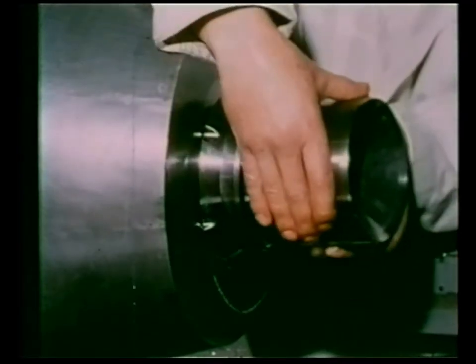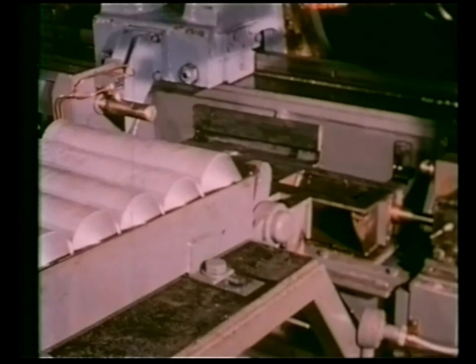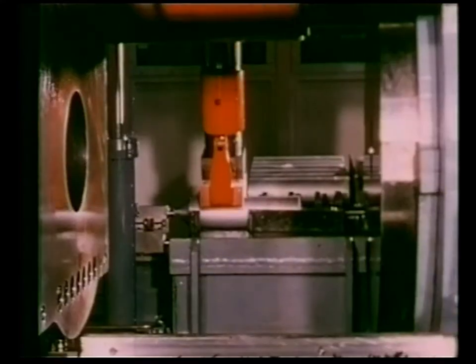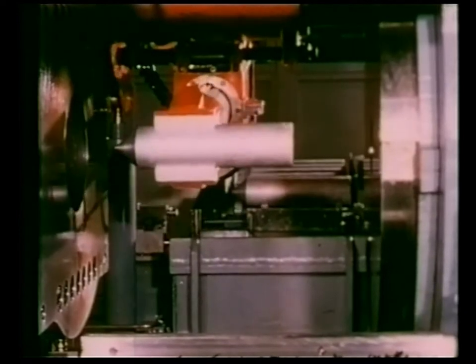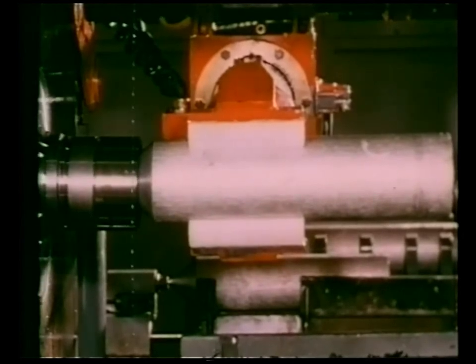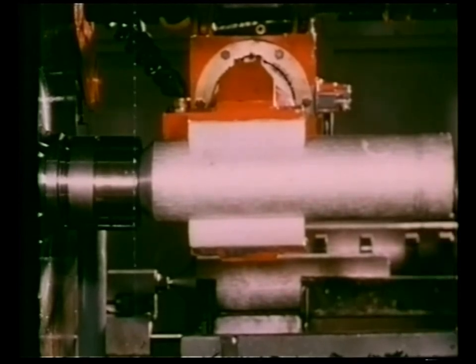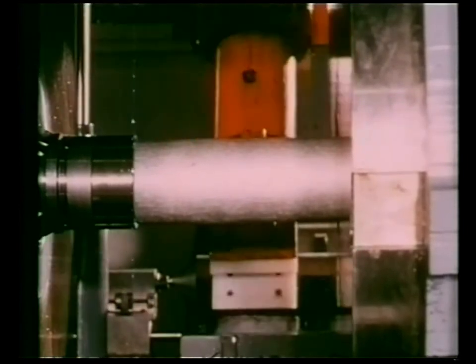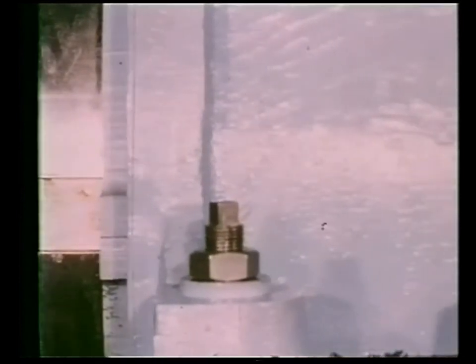The first step in carrying out an extrusion is to set the die in place on its carriage. A billet is then delivered to the loader, which picks it up and aligns it with the die. The die is moved from the left on its carriage and located round the nose of the billet. The billet container and augmenting ram move from the right over the end of the billet. The loader jaws are retracted and the assembly with the billet inside is positioned against the end housing.